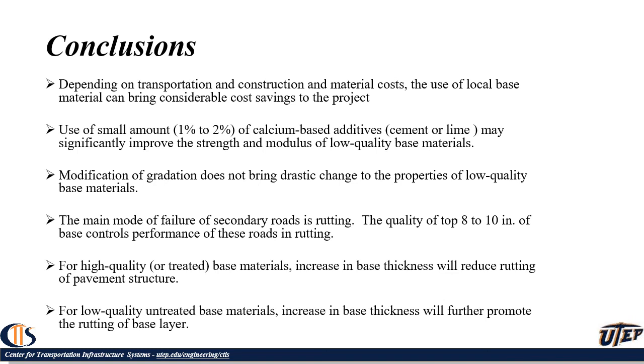For high quality or treated base materials, an increase in the base thickness will reduce the rutting of the pavement, as we always consider in the design. But for low quality untreated base, increasing the base thickness will basically transfer and promote the rutting of the base layer.